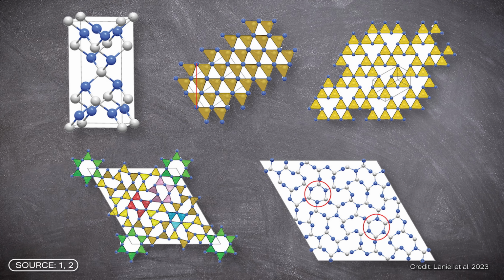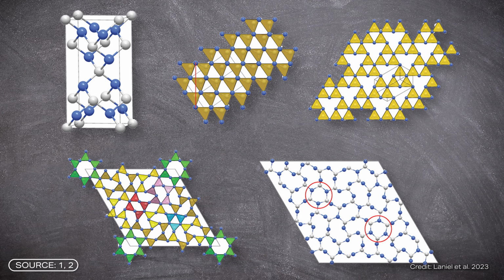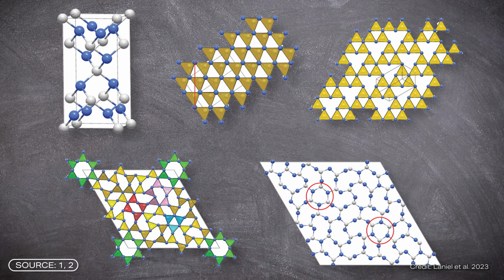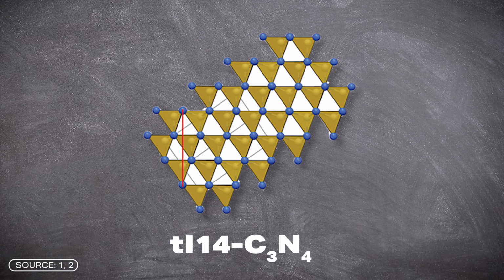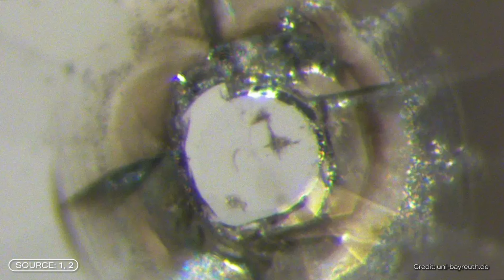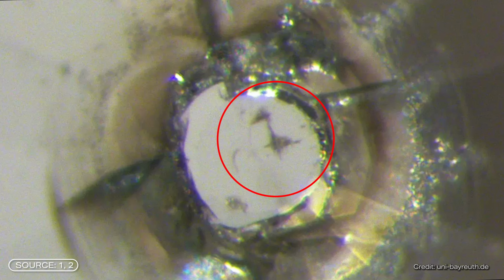The crystal lattice differs between the 4 materials, but the basic building blocks are always these tetrahedrons of carbon atoms with 4 single bonds and nitrogen atoms with 3 single bonds. The crystal structure of the first material is very dense and symmetrical. And it was precisely this material that they used for their endurance test. To do this, they placed it back in the diamond press and subjected it to extremely high pressure again. This test was quite successful as it damaged the diamond press. In this photo you can see the areas where the surface of the diamond was indented.